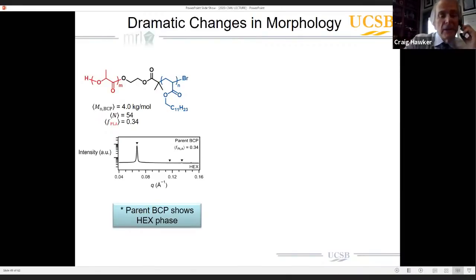Do we see an effect on the morphology? And do we observe unique new morphologies? So again, this is our starting workhorse. This diblock copolymer has a fraction of PLA of 34%. And as you would expect, and this agrees with literature, it's a parent hex phase. So cylinder phase, exactly what you would expect.